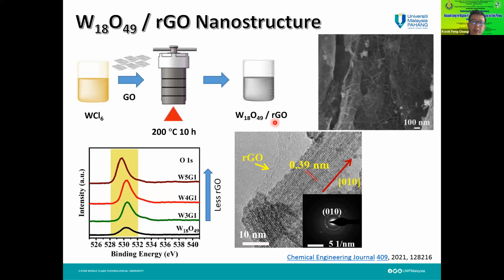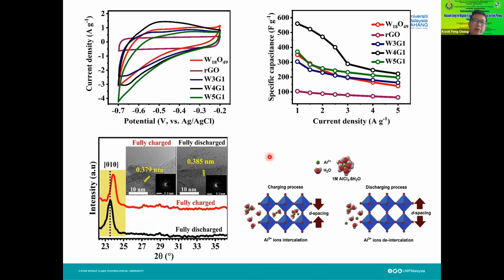So that's the morphology, and then we found that there's nothing much change in the crystal spacing when we put the reduced graphene oxide into the structure. We make a composite of the tungsten oxide and the reduced graphene oxide. And then we compare in terms of the specific capacitance. You can see the specific capacitance for the tungsten oxide, whereby that is a different ratio.